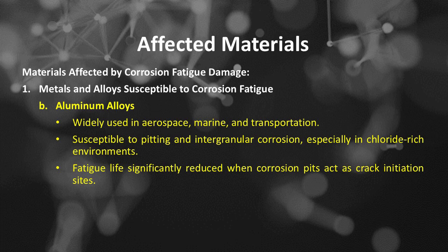Metals and alloys susceptible to corrosion fatigue. Number B is aluminum alloys, widely used in aerospace, marine, and transportation, susceptible to pitting and intergranular corrosion, especially in chloride-rich environments. Fatigue life is significantly reduced when corrosion pits act as crack initiation sites.